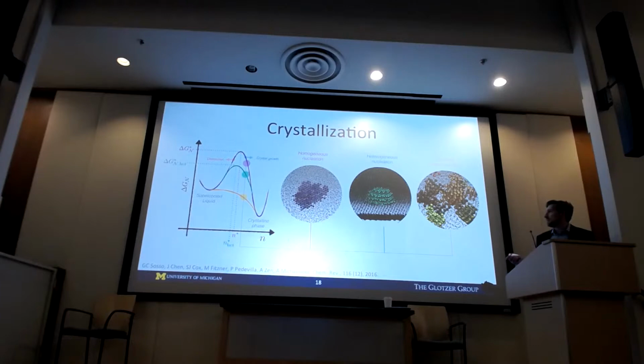But while the particles inside of this nucleus are very happy, the ones at the surface are not, because they are kind of forced into this structure, but they still need to deal with all of these particles outside of this nucleus and in the fluid, and they don't have the freedom to move around in any way they want to accommodate whatever they're facing there. This is what we describe as the surface of this nucleus, and then everything else is the bulk. And that is kind of the crux of the problem.